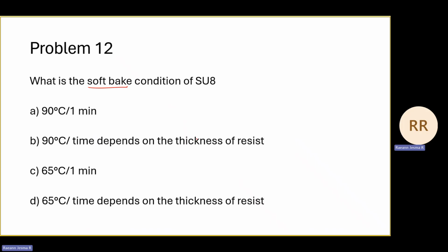Okay. So SU 8 is a negative photoresist, or like we can say it is a negative resist, and so there are various types of SU 8 resist. Depending on the viscosity, they have various product lines. So one of them is SU 8 10, by varying the spin speed, you can coat between 10 to 25 micrometer. Again, since the thickness of the resist is varying, the amount of solvent that is present in the entire resist will also be different, right?